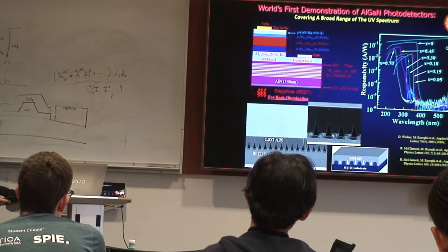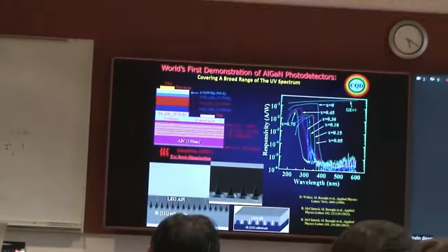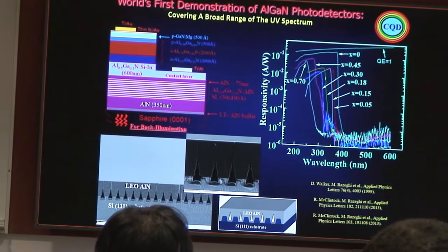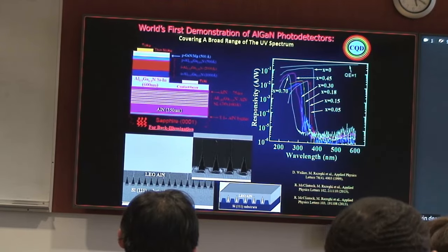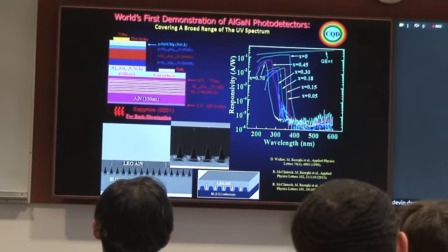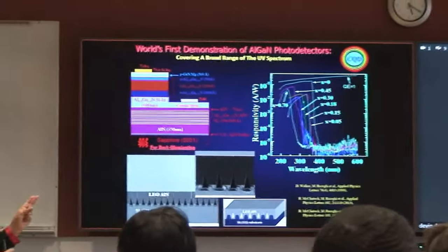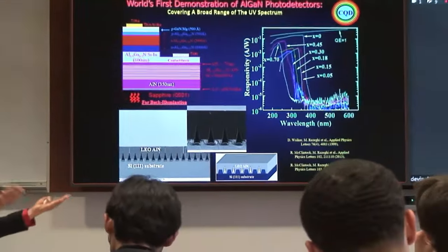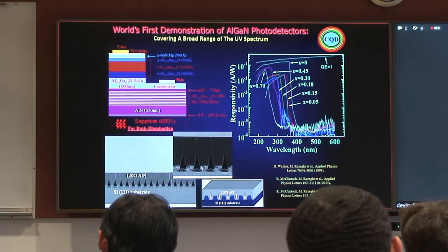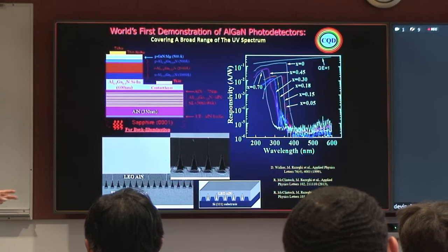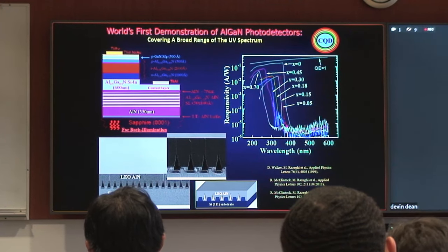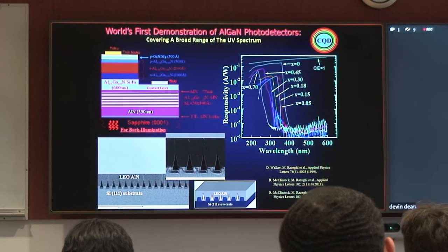First, the nitrides unfortunately have a direct energy gap, but they are not zinc blende; they have the wurtzite crystalline structure. And nobody can make a substrate from aluminum nitride. That is the challenge for the young generation in the future, because for 50, 60 years nobody has been able to make it. So we use sapphire or silicon substrates, and then you have defects and dislocations because of the lattice mismatch.